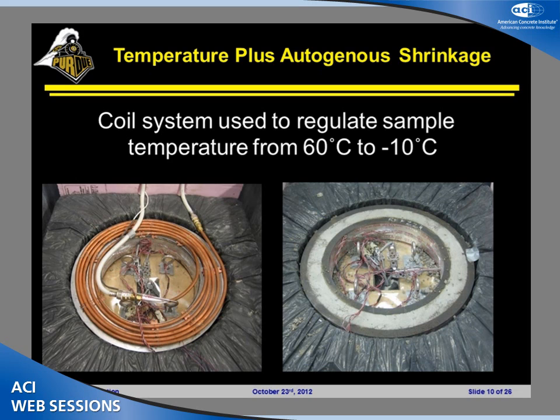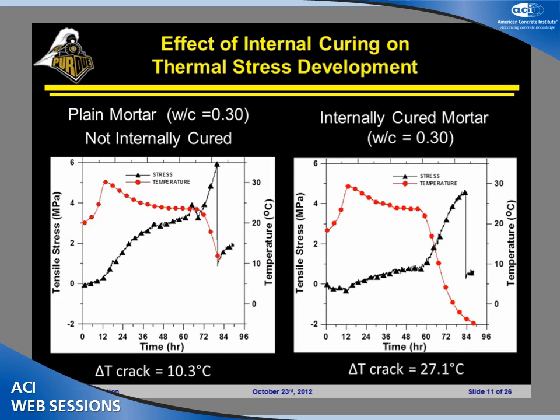The other thing that I want to point out is these rings are not made out of steel. These rings are made out of a special kind of steel called Invar, which doesn't change dimension very substantially as the temperature drops. So the restraint is staying constant, and we're dropping the temperature, so the concrete will be what's wanting to move during that particular test. So a typical result that we may see for some of these concretes that we're looking at, and we'll talk as we go through, we'll essentially be comparing a plain and an internally cured system.